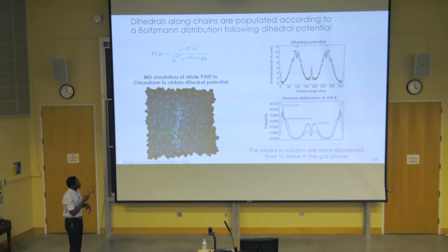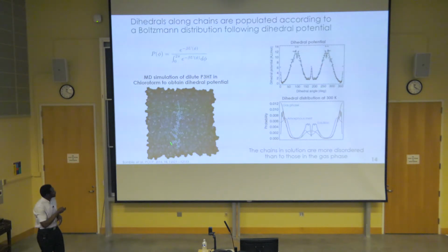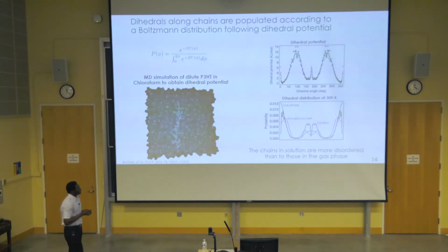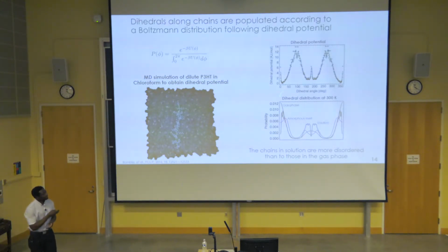and here is a picture of the simulation of a polythiophene, a P3HT chain, in a chloroform solution. And from these simulations, we extract the dihedral potential, and the dihedral potential is then used in this expression to generate the distribution of dihedrals along a given chain at a given temperature. And this dihedral distribution is used to populate the dihedrals for the chain in a given medium.